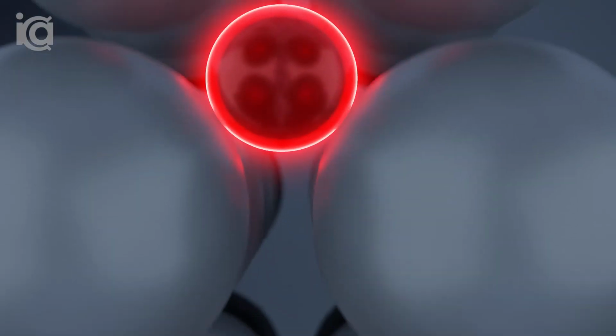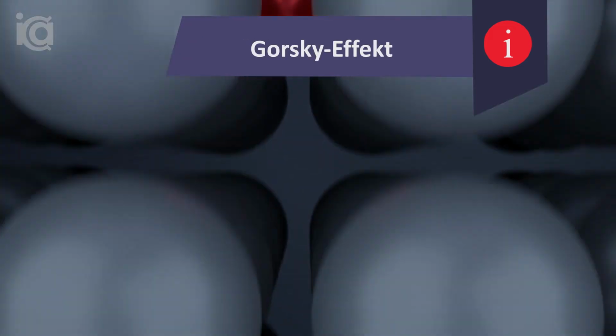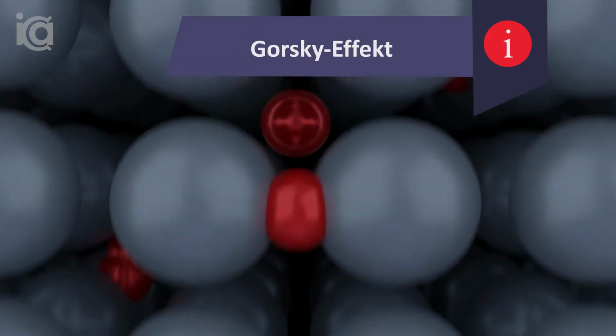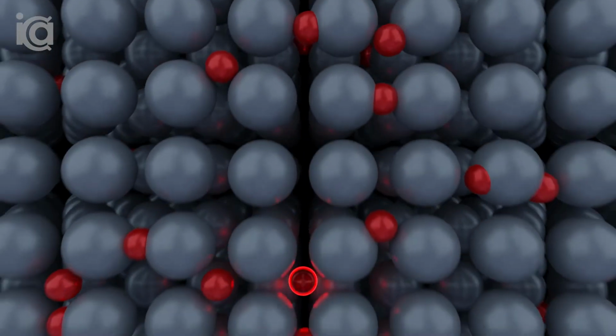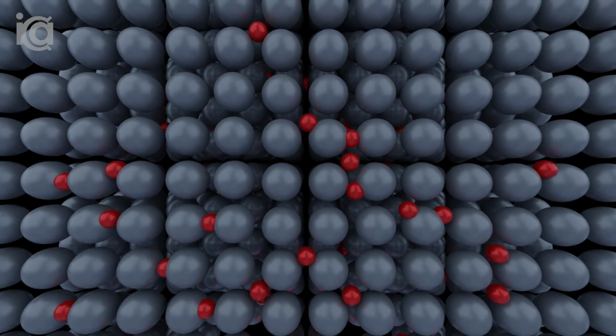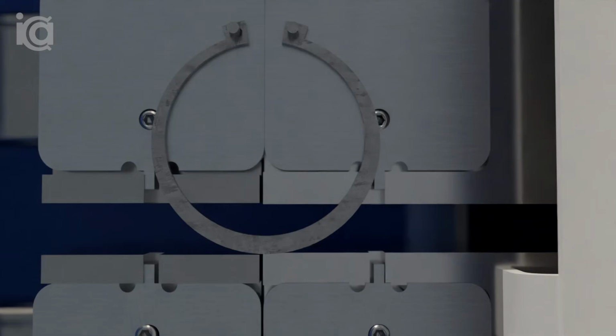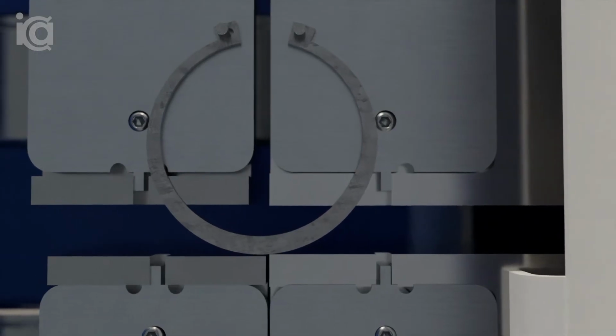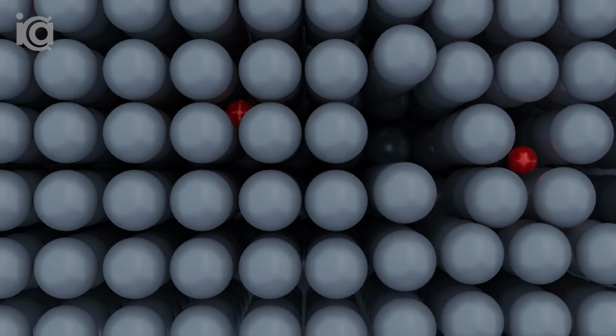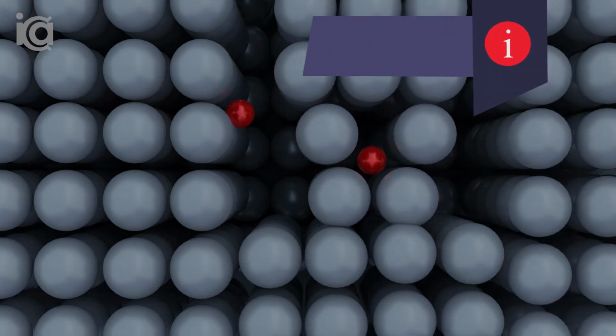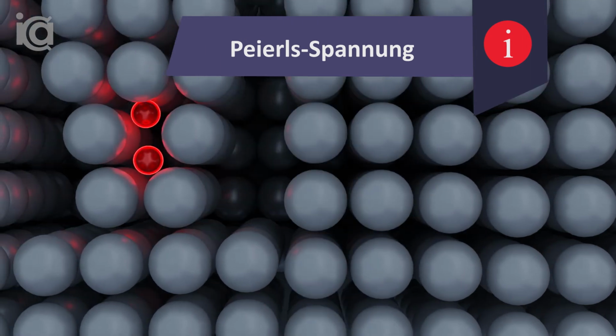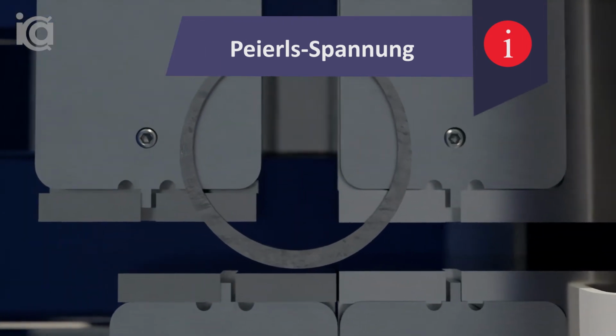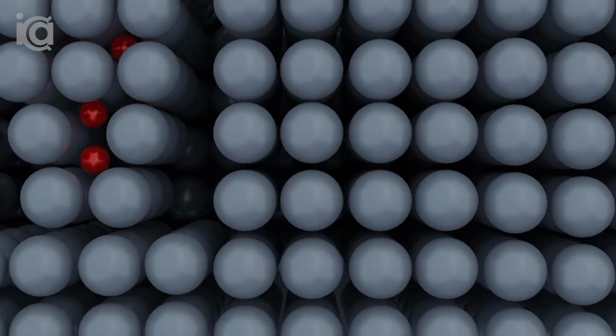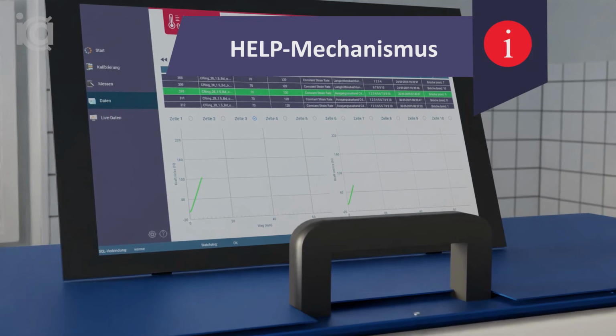The diffusion of atomic hydrogen into the metal structure is positively affected by dislocation motions and tension gradients. Therefore, inhomogeneities in the crystal structure, such as notches and microcracks, enhance hydrogen diffusion and result in a local hydrogen enrichment. During the tension bending test, hydrogen dissolved in the crystal structure decreases the activation energy for dislocation movements after crossing the elasticity region of the material. Due to the dislocation motion in the tension bending test, atomic hydrogen is transported to areas of increased tension gradients, for example cracks and notches.